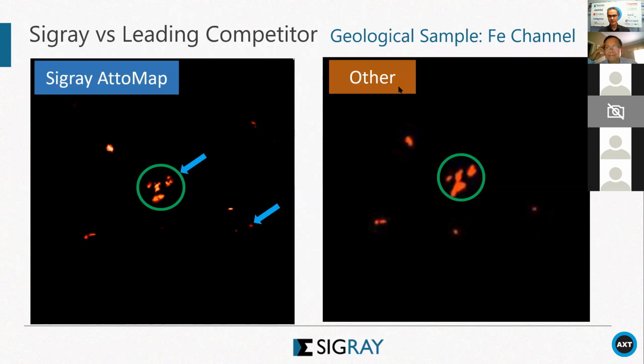Okay. For quantitative analysis, how does it cope with the matrix corrections to account for different X-ray penetration of different energies of the incident beam and generated X-rays? Are standards required? We usually do two things. One is that for a known sample, we have a fundamental parameter approach. We use a major element to know what the material matrix is. To do that, the absolute accuracy is probably going to be about a few percent, not better than 1% typically. But if you have a reference standard, we can do very well. Below 1% is reasonably easy.